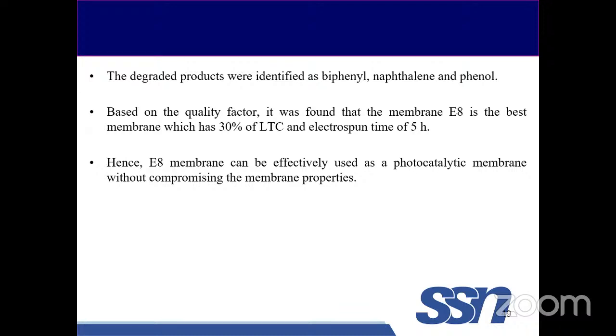As I already mentioned in the starting, right, there are 2 drawbacks that are available. Whatever photocatalysts are used in the dye industry are being discarded after degradation in the water bodies, right? So, as we incorporate these photocatalysts in the membrane, we can recover those photocatalysts back for utilization, right? So that can be overcome, and we have an efficient filtration efficiency. As the fiber sizes are smaller, we have a higher amount of encapsulation efficiency, right?